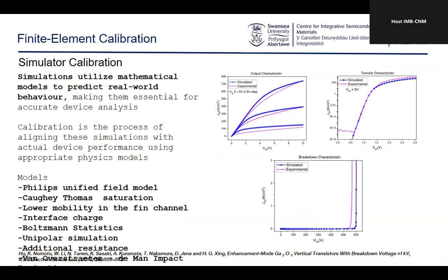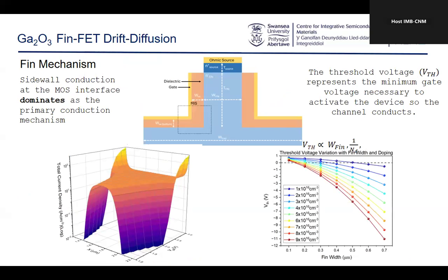And finally, some gallium oxide work. At the moment, gallium oxide for us is still in the design phase. The slide's gone strange here again. My apologies. But basically, what my student is working on at the moment in gallium oxide is calibration of finite element models in commercial packages like Silvaco. Based on the classic semiconductor models for mobility, interface states, and unipolar resistances, we've managed to fit some experimental curves taken from literature, from this paper, with experimental output, transfer and breakdown characteristics. However, we now need to show that these work at increased temperatures.